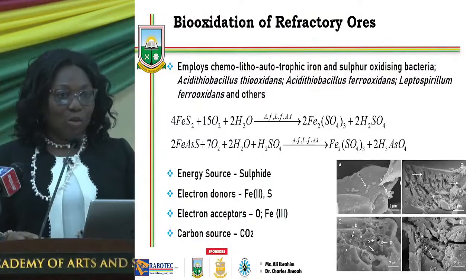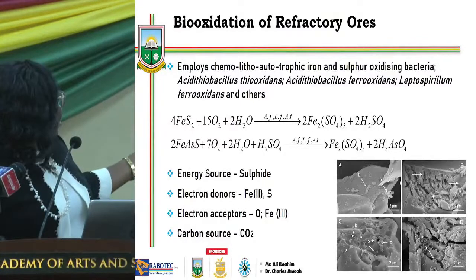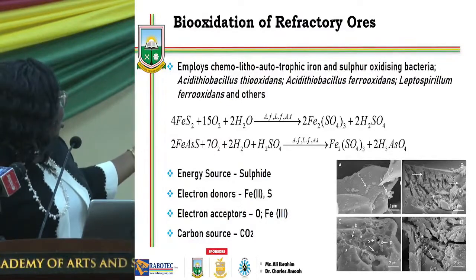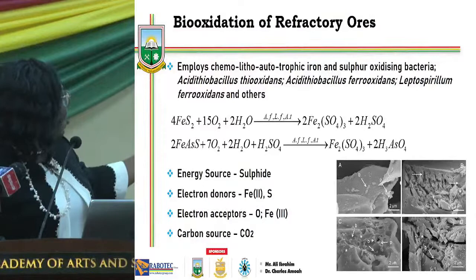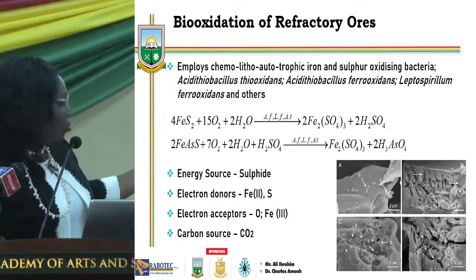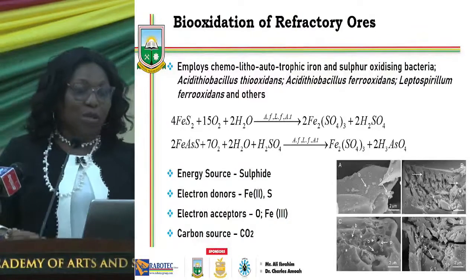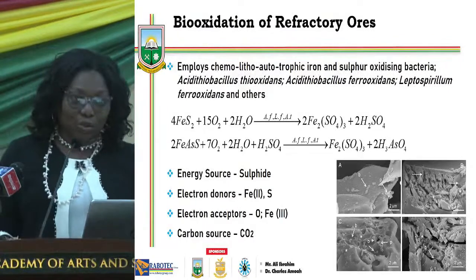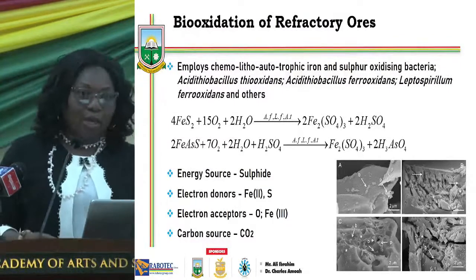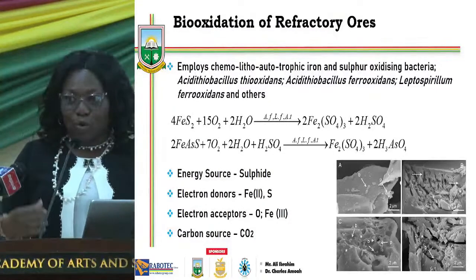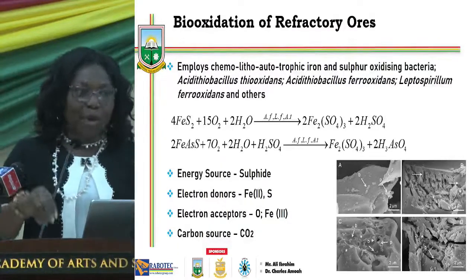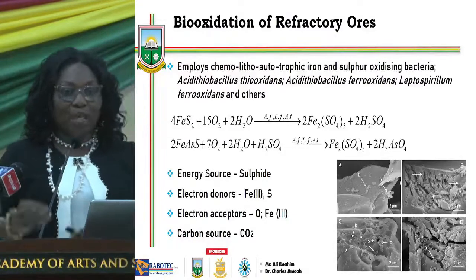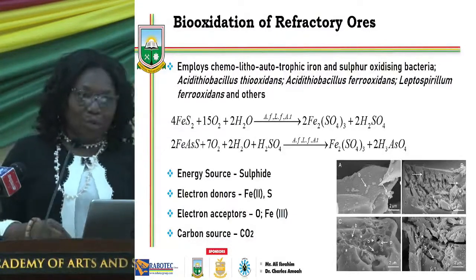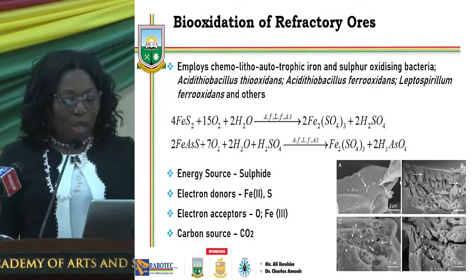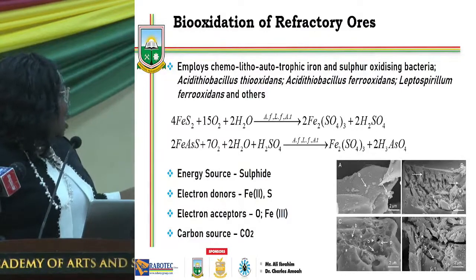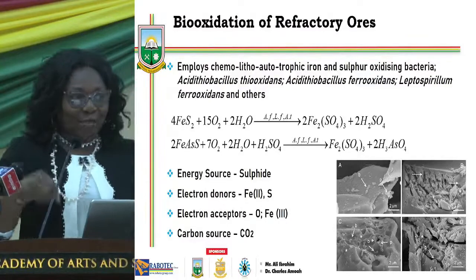So we have iron and sulfur in sulfide. So if you look at this equation, it's the same components we used in roasting. But in this case, we are using microorganisms to oxidize the pyrite and arsenopyrite. So these organisms will use iron 2 and elemental sulfur as their electron donors. They will use oxygen as electron acceptor. Because they are living organisms, they need carbon for their cell growth. Instead of using organic carbon directly, they don't do that. They want to make their own organic carbon from inorganic carbon. And the inorganic carbon they use is carbon dioxide. The diagram we see here is just showing how they are able to chop the sulfide from the rock.